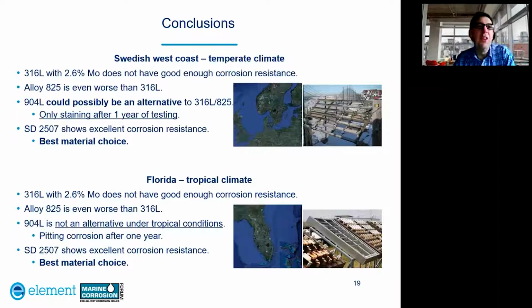So I'm jumping through the presentations and going to the conclusions. The conclusions were at the Swedish west coast, which was a temperate climate. The 316L stainless steel with about 2.6% molybdenum does not have good enough corrosion resistance. So the alloy 825, which has a high nickel content, has even worse corrosion resistance in this environment than 316L. So the 904L, which is a superaustenitic grade of stainless steel, could possibly be an alternative to 316L or 825, since it only showed some staining after 1 year of testing.